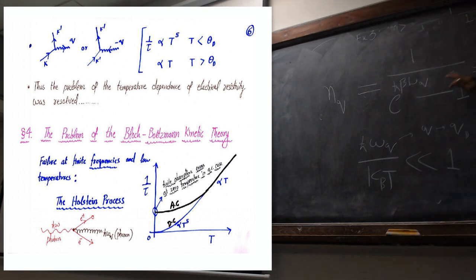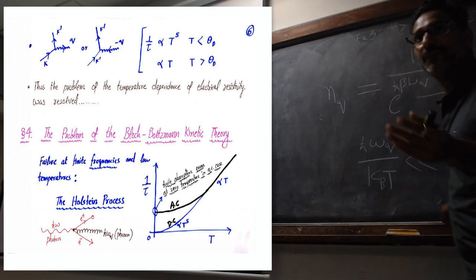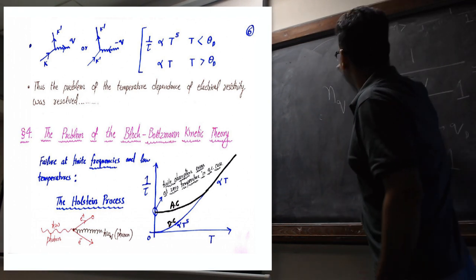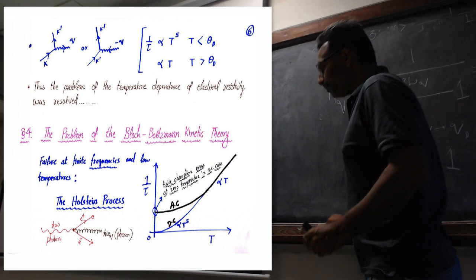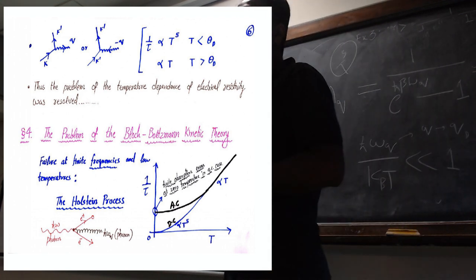But at low temperature, it's a little complicated. At low temperature, the number of phonons goes as T cube, like the T cube behavior of heat capacity due to lattice vibrations. The heat capacity goes as T cube, so the number of phonons goes as T cube. But why should it be T to the power 5?